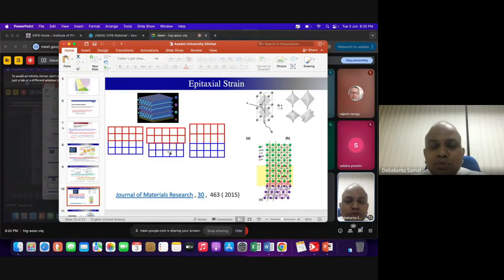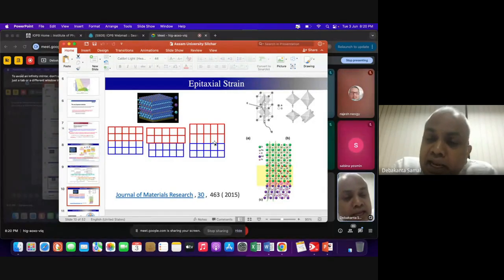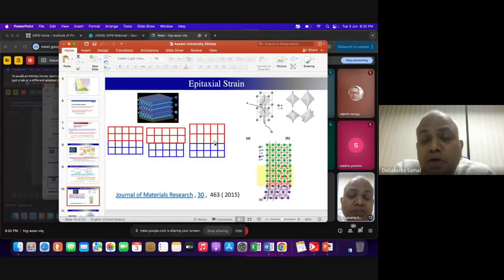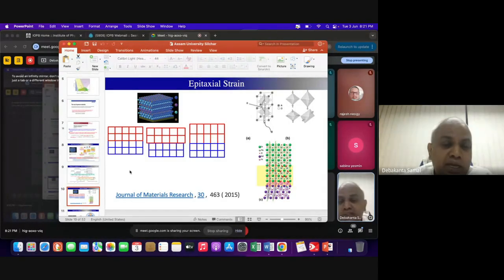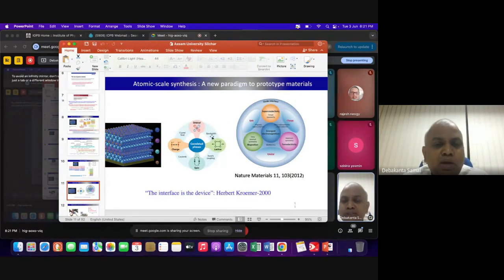But in this case, the blue one and the red one have different lattice parameters. So this is a kind of tensile strain, it is expanded. Similarly, here you will see another strain because it is compressed. Because of this strain, the energy of the system competes with the other energy scales that I showed you, because in a solid there are various kinds of energy scales. Because of this, in the laboratory you can tailor this strain energy, and it can give rise to various new phenomena. This is what people have done.